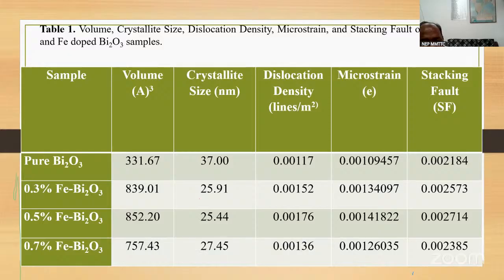And these are the lattice parameters, cell volume, dislocation density, which go on increasing and then suppresses. Its microstrain is again calculated, and stacking fault. And it is found that it is enhanced initially and then there is a minor change in this.